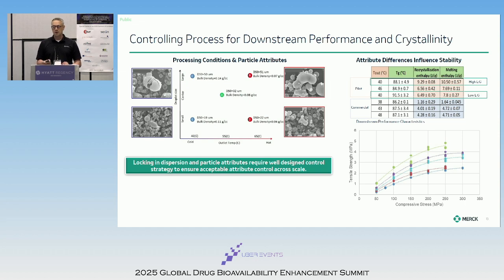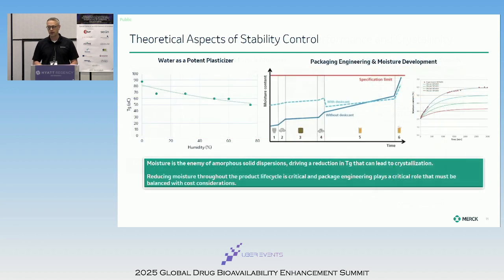And we can also see notably subtle differences even in terms of the DSC characterization and characteristic aspects of those materials that we produce that can be leading indicators that there could be shifts in stability, right? Looking at the melting enthalpy as a function of our outlet temperature in this case, we did see differences, although they didn't manifest in any significant issues around the ability to control. It does suggest that the spray drying process carries implications that need to be understood when developing products with the technology. Now, we've made the dispersion particles, they're uniform.